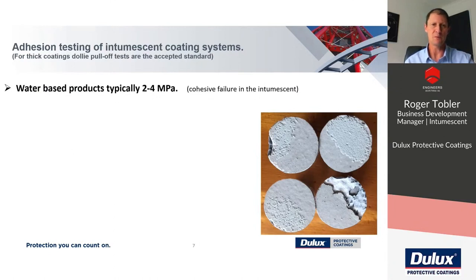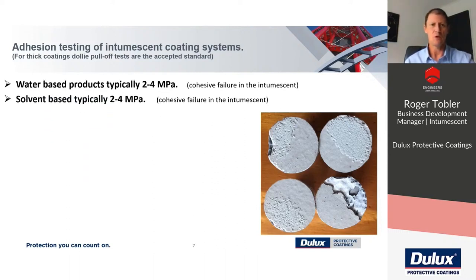So we find that water-based products typically achieve 2 to 4 MPa. Cohesive failure that is listed on the slide there is the failure of the intumescent. So it's not the primer, it's not the top coat, but it's the intumescent that gives way. Looking at solvent-based intumescents, you get similar values, 2 to 4 MPa, and again, it's cohesive failure in the intumescent. So the intumescents are designed to expand when they're exposed to heat, and as such, they don't have great cohesive strength under normal atmospheric conditions.